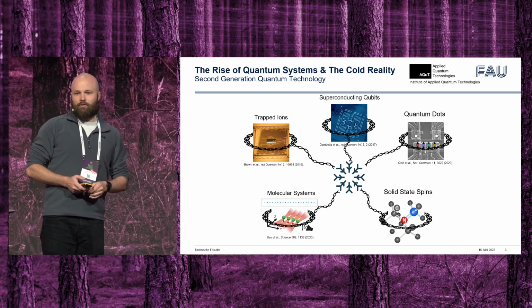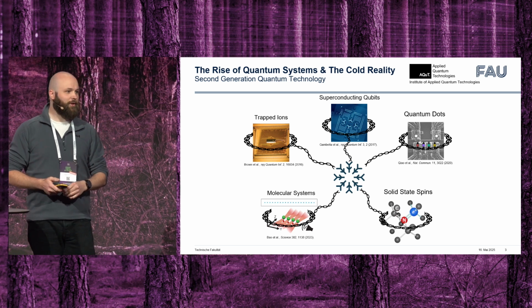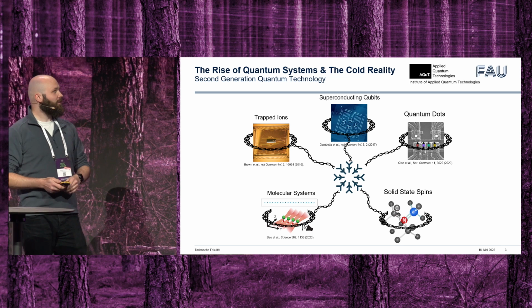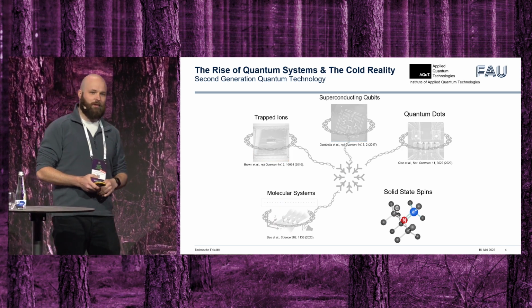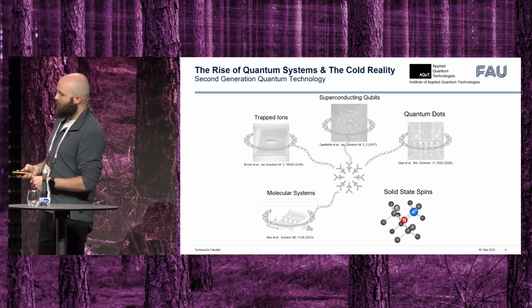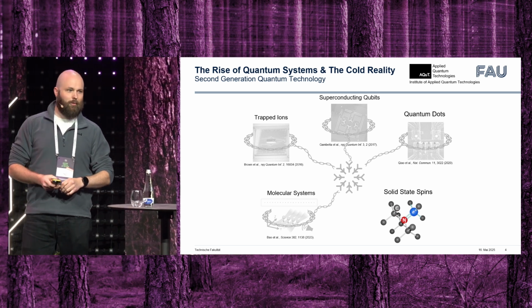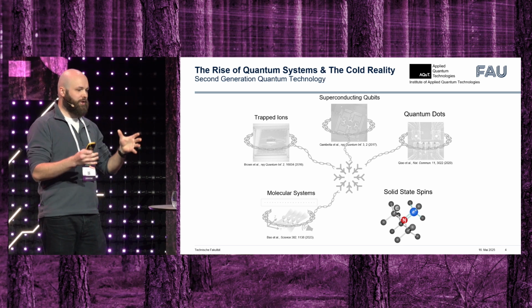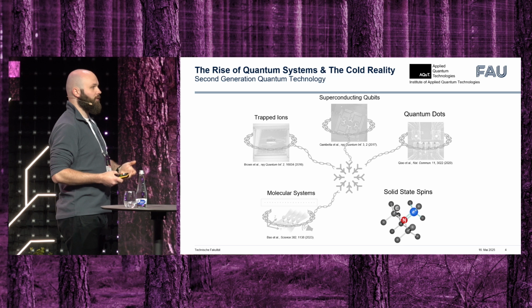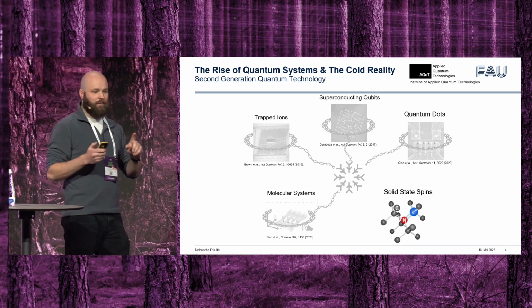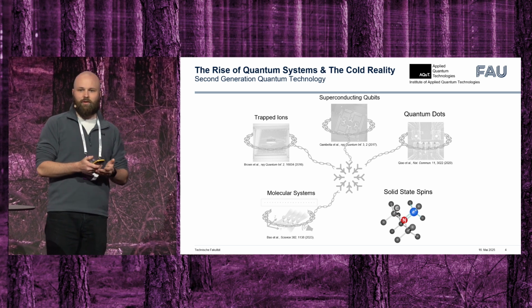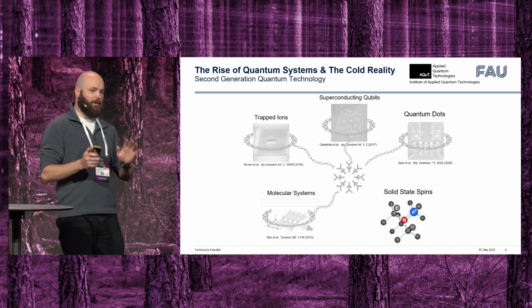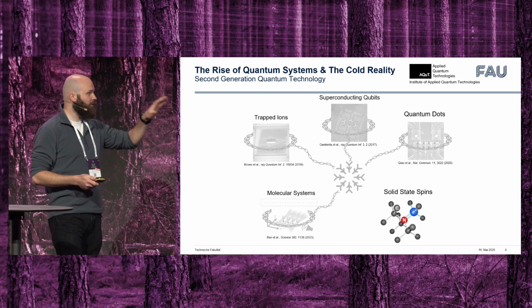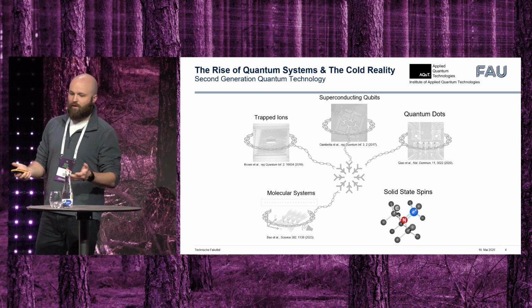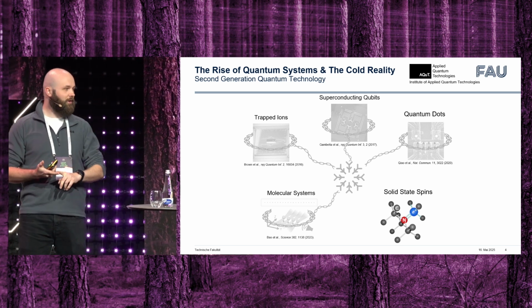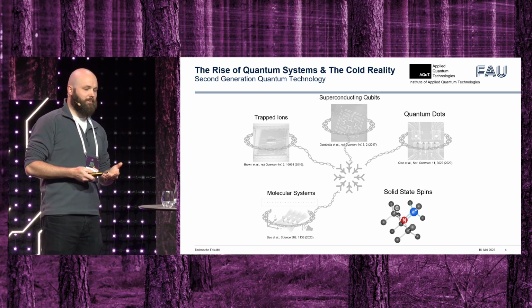Now, if we want to talk about real-world applications, using an ultra-high vacuum and cryogenic temperatures kind of defeats the point. So this is where one of these systems, namely solid-state spins, comes in with a major advantage. And the interesting part here is that we still use these spin systems that observe quantum mechanic phenomena, but since they are embedded in this very rigid crystal, it shields them from macroscopic noise and from thermal fluctuations. And this allows these solid-state spin systems to observe coherence times that go into the micro to milliseconds, even at room temperature. And this is the big advantage, because these systems don't require a high vacuum, because the spin state is encased in this solid-state material, and it allows us to perform our measurements at room temperature.